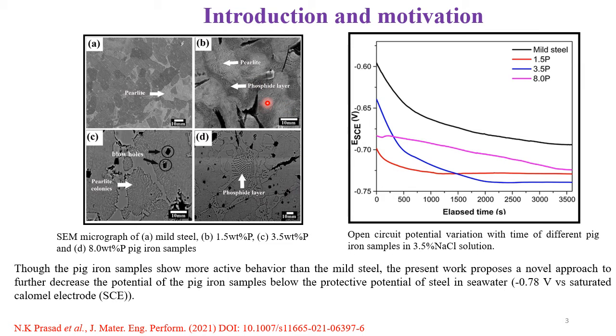So this is the previous work which I have done during my PhD, and it has been observed that the pig iron sample shows more active behavior as compared to the mild steel, and as a result of that, they show promising behavior as a sacrificial anode. As could be seen here, we have used different phosphorus containing pig iron samples with 1.5%, 3.5 and 8% phosphorus, and due to the inhomogeneity in the microstructure, they show more active behavior than the mild steel. Along with that, the corrosion potential of all these pig iron samples was more active as compared to the mild steel, as a result of which they show more promising behavior as a sacrificial anode.